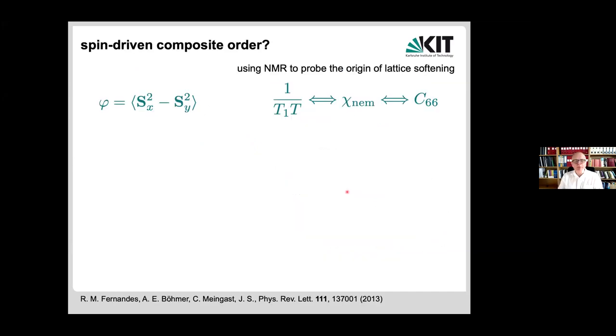And maybe one last comment on this iron-based story is whether there is indeed a way by which you can pinpoint that there is a magnetic fluctuation, a primary order fluctuation, causing the second rank tensor to condense. If you have magnetic fluctuations, which you would, for example, measure through an NMR relaxation rate measurement, you could conceive that it impacts the nematic susceptibility, because it's just a composite of the spin degrees of freedom, and hence would impact the elastic constant.